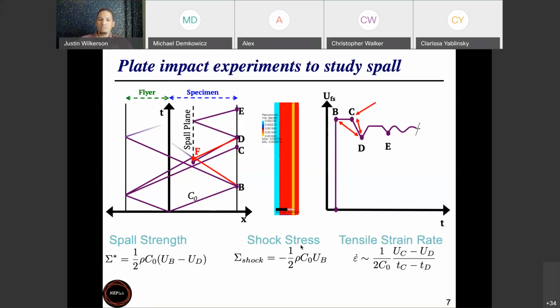And then the last one that is really important is the tensile strain rate. Okay, so this is the average strain rate that the material experiences in the spall plane as it's ripping itself apart. So as this yellow damage region is forming, what is the strain rate that's pulling that crack open? And that's roughly approximated as 1/2 the inverse of the wave speed, and then we're basically looking for this slope here. So we take the difference between velocity at C and velocity at D, divided by the time at C minus the time at D. And that will tell us roughly the strain rate that the material was experiencing.